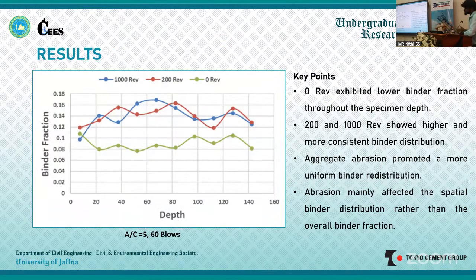This figure shows the effect of aggregate abrasion on binder distribution at an aggregate to cement ratio of 5 and a compaction level of 60 blows. The green line represents 0 revolutions, and the blue and red lines represent 1000 revolutions and 200 revolutions. We can see that the specimen without abrasion shows lower binder fraction throughout the specimen depth. In contrast, the specimens with 200 and 1000 revolutions show higher and more uniform binder distribution.